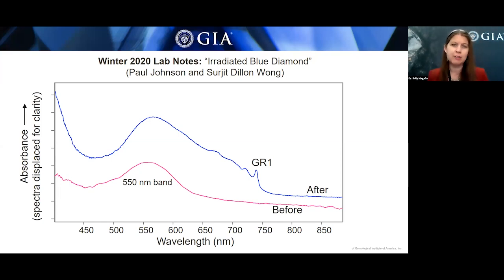In the absorption spectrum for the blue treated diamond, the combined effect of the 550 nanometer band absorption along with the GR1 absorption and its sideband causes this near violet color. And I really think this is a great example of color engineering, and I can only suppose that it was intended to be an interesting experiment by the treater to gauge what might be possible when a natural diamond that is not normally chosen for treatment is subjected to laboratory radiation. And it certainly results in a diamond that is generally not seen in nature and not often attempted within the trade.